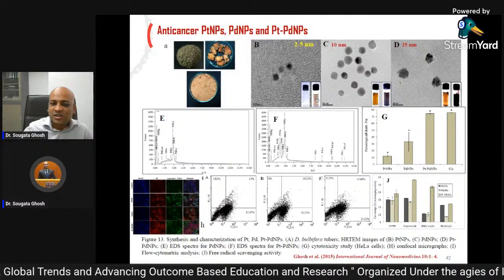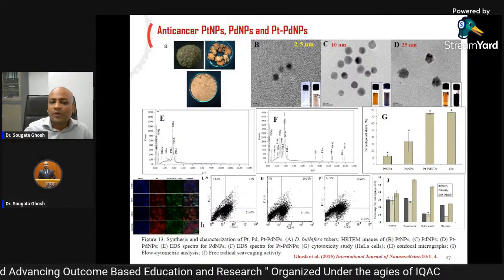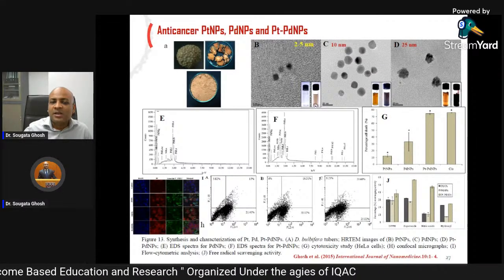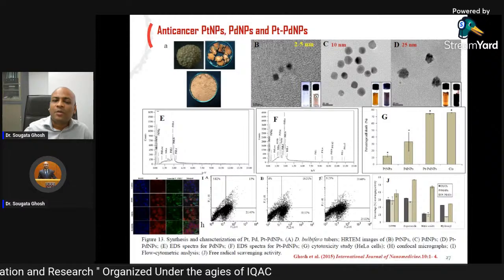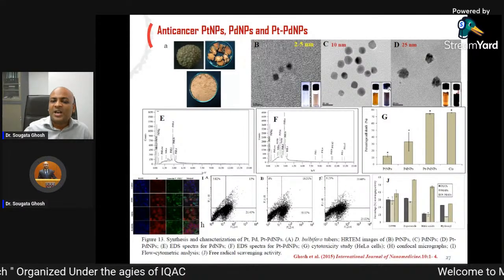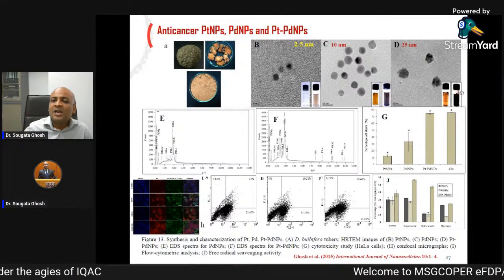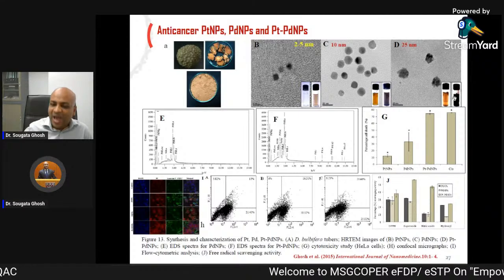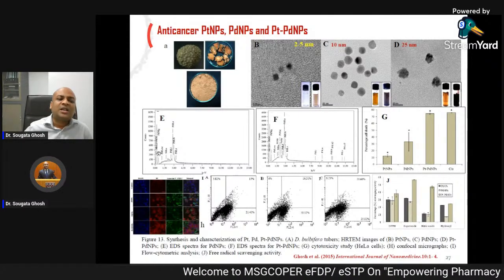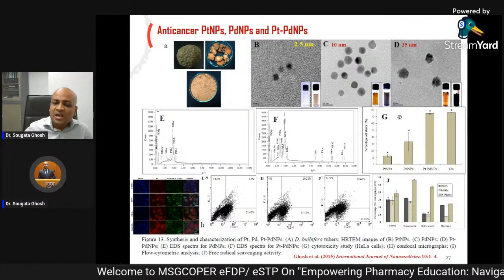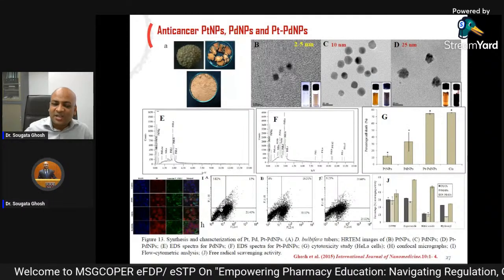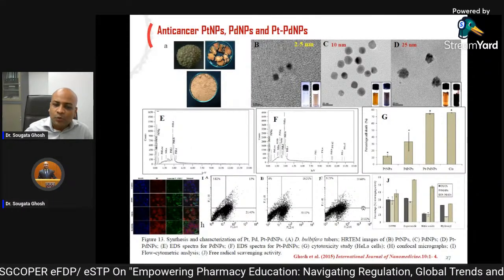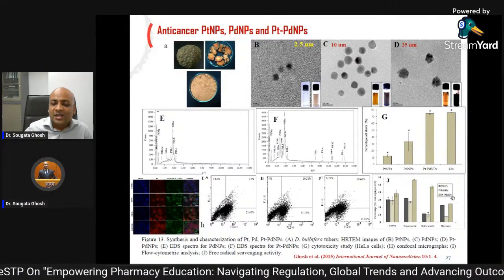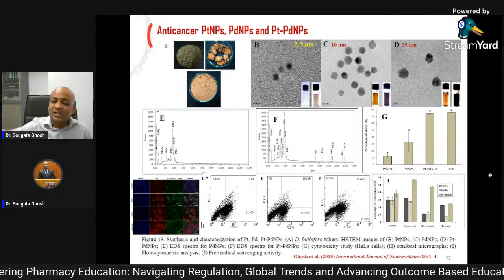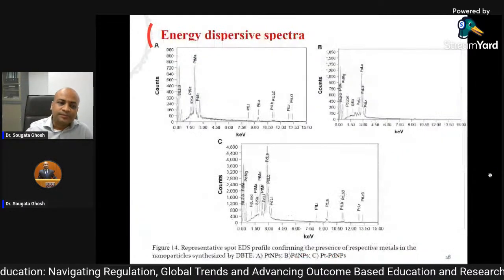You can see the color change when the platinum nanoparticles were formed. This is platinum chloride, and after platinum nanoparticles are formed, this is the color. This is palladium nanoparticle, black in color. Platinum palladium, intense black. So we checked EDS and then did the anti-cancer activity, tried to prove it, and then we did antioxidant activity, checked the antioxidant activity.